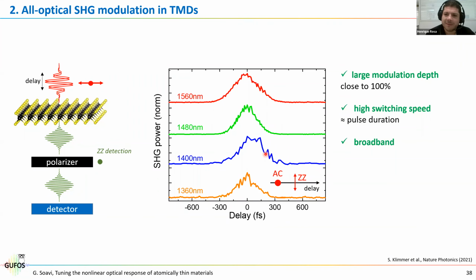Okay, well, it is a good idea, because then the optical band gap is lower compared to the other conventional TMDs, right? Another option, and this is what people have done, is if you have a Ti:sapphire, we have an ytterbium, but if you have a Ti:sapphire at 800 nanometers, or tunable between 700 and so, then you can also use MoSe2 and WSe2, because if you pump at 750, you are above gap for both. But then you need a Ti:sapphire, and we don't have it.